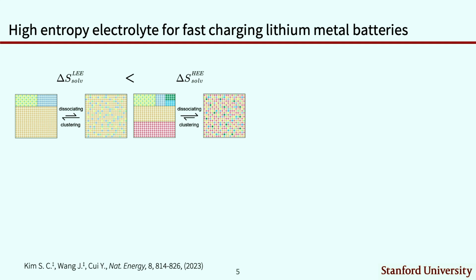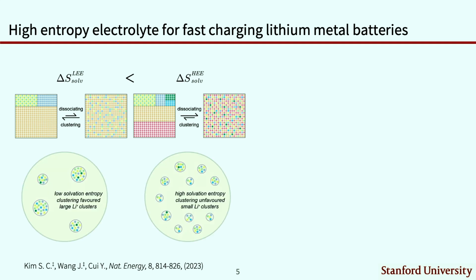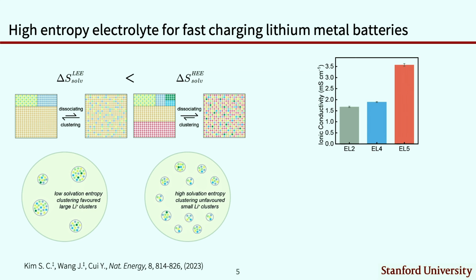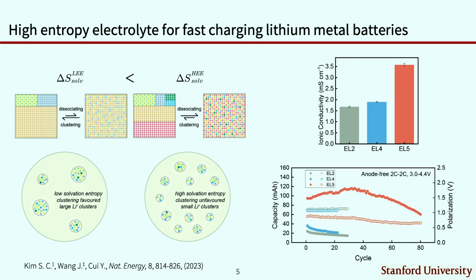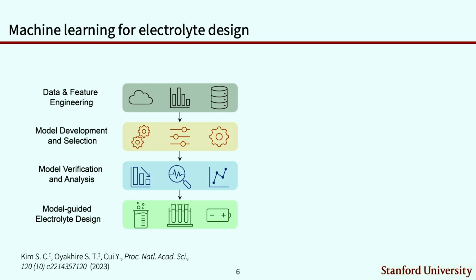Moving on to the next one. Ion transport is, of course, a key property of electrolytes. And here we introduced this high entropy electrolyte, where we actually tune the entropy of the electrolytes to boost transport properties. Until this work, entropy had been more or less neglected in battery electrolyte design, but we showed that by tuning entropy, you can significantly tune how the ions behave in the electrolyte. With that, we can very significantly increase the ionic conductivity, and the fast charging performance of these lithium metal batteries can be very different as well. So that was on the molecular level design of electrolytes.